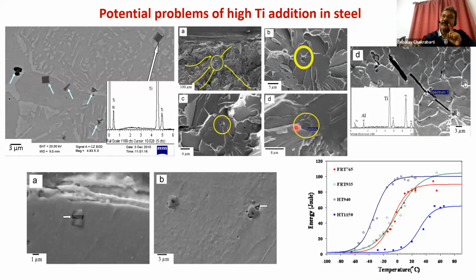In titanium, also, this is a huge problem, because titanium forms a very stable titanium nitride precipitate. And if there is segregation, naturally those precipitates can become many in number and large in size. So in this image, you can see so many titanium nitride precipitates, cuboidal shaped, hard and brittle particles. So those can initiate cracks very easily.